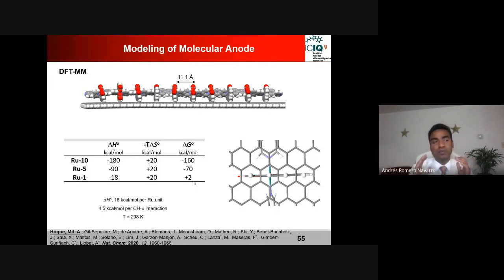And we know that any process can be downhill or easy if we have a negative delta G value. So with one molecule, it is not favorable. It means that if you are trying to put a mononuclear compound onto a graphite surface, it will not stay. But what we found is that if we increase the size, say if you have this pentamer, then each unit has 4 CH bonds, and those 4 CH bonds give 90 kcal per mole binding enthalpy of energy, and that is negative, so that is favorable.